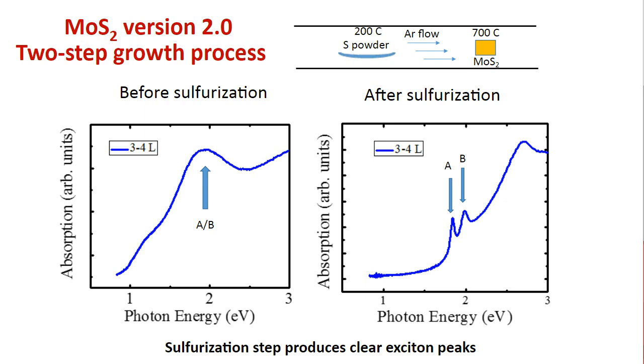And you can clearly see that this broad peak at 2 eV has now changed to 2 sharp peaks, and these are the excitonic peaks that we are looking for. So immediately it told us that the sulfurization step is working, and it produces these clear excitonic peaks that we expect to see for MoS2. That was basically the basis of more follow-up work that I'm going to talk about next.